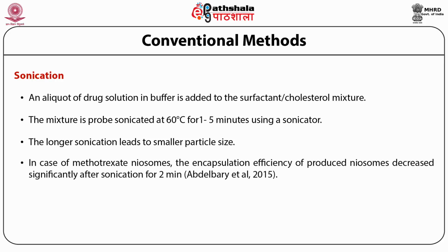It has been observed in the case of methotrexate niosomes that the encapsulation efficiency decreased significantly after sonication for 2 minutes. Also, sonication results in small unilamellar niosomes. Therefore, the sonication time affects the encapsulation efficiency and the size of the niosomes formed.